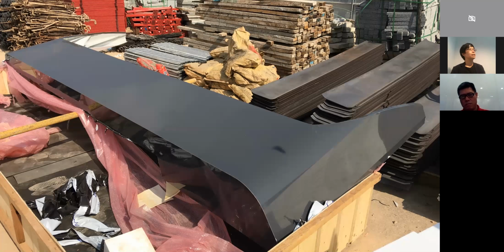But with the coil coating, there's a limitation of the maximum thickness. I think it's about 1 millimeter. If you go to the next, you start seeing the reflection of the panel, which is exactly what we are looking for, highly reflective. And it also plays around with the curves. However, we also realized that by specifying a coil coating, we run into an issue because you coat the panel first and then you assemble.